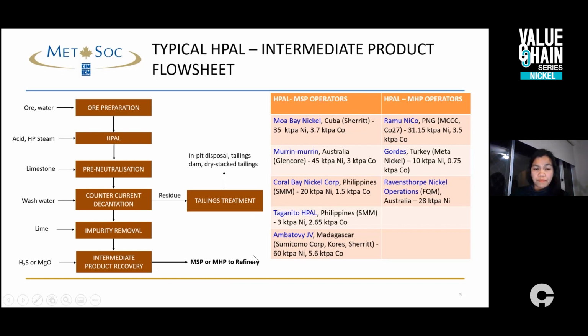So the residue and the tailings from the high pressure acid leaching are in a slurry form. And it still contains a lot of dissolved heavy metals. So the typical route for that is to treat the heavy metals and drop them out from the solution at a very high pH, so that the concentration of the heavy metals meets at least a minimum standard, the World Bank standard. And the slurry is then disposed either in open pit, because the majority of the laterite operations have a lot of open pits that are already barren of ore, and that's where the slurry can be contained.